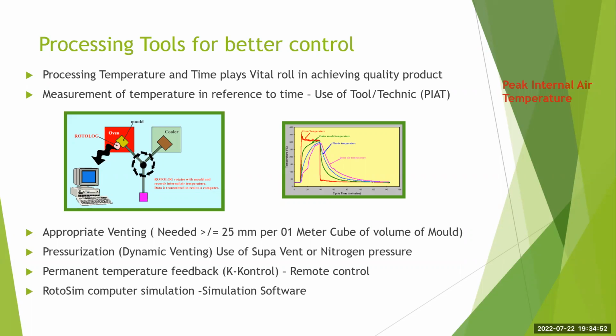Now, if you have improper venting, you create pressure in the mold, and sometimes we have seen instances where the mold has bulged and exploded. That happens because when you heat the material, it expands. And if the venting is not proper, then probably the mold becomes distorted and collapses.